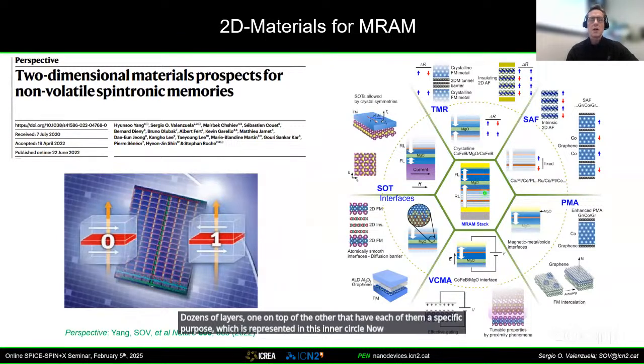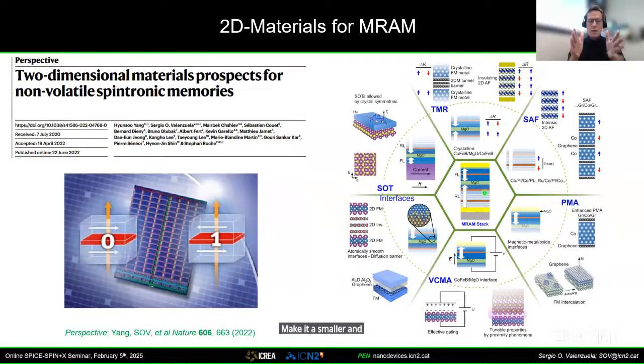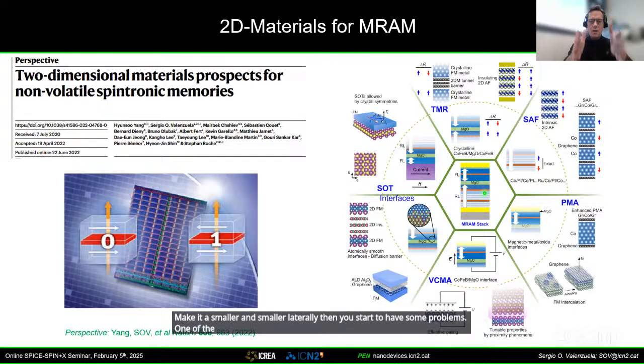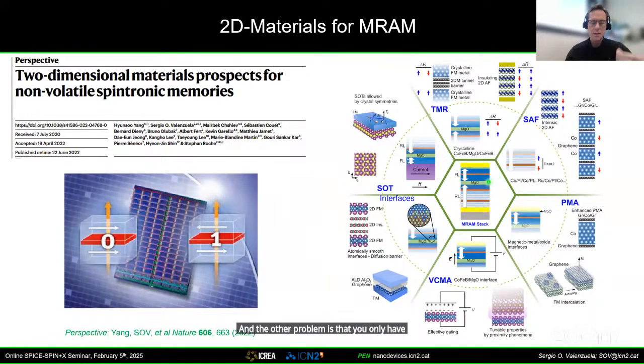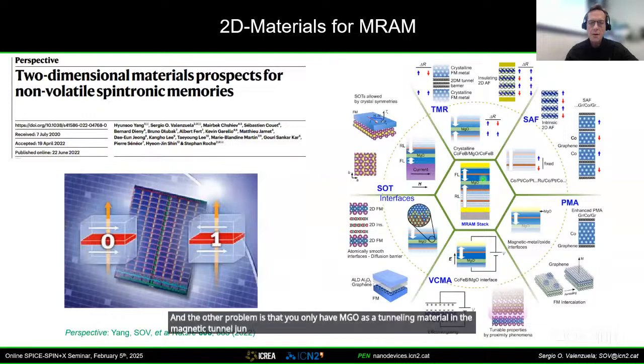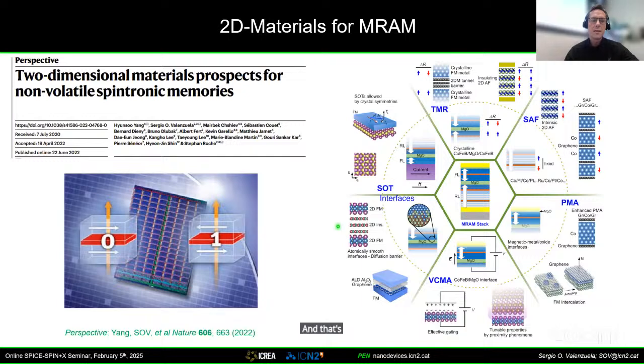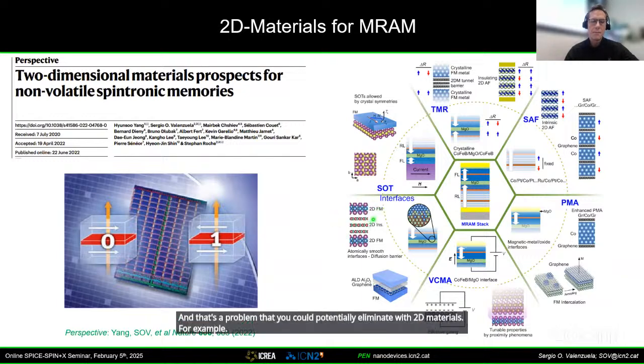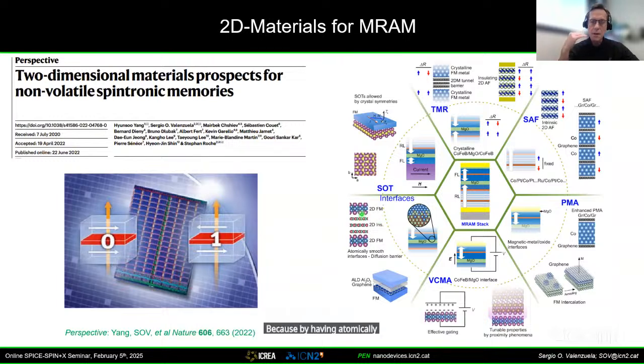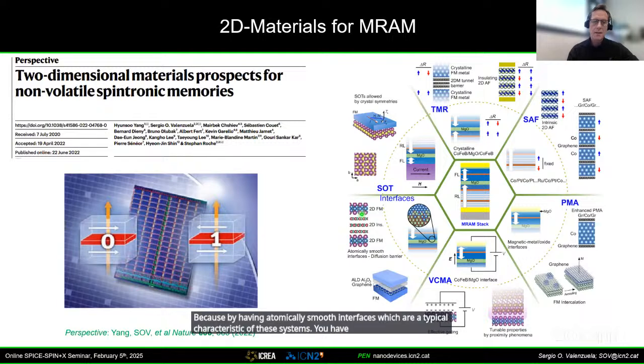Now, if you want to scale this structure, make it smaller and smaller laterally, then you start to have some problems. One of the problems is that it becomes very tall, and that's difficult to handle. And the other problem is that you only have MgO as a tunneling material in the magnetic tunnel junction. You have certain intermixing of the material. There is a roughness inherent in the 3D materials that we use. And this roughness becomes more important when you scale down because you have to reduce the thickness of the barrier so that the resistance does not go up too much. And that's a problem that you could potentially eliminate with 2D materials, because by having atomically smooth interfaces, which are a typical characteristic of these systems, you have layers separated by van der Waals gaps.